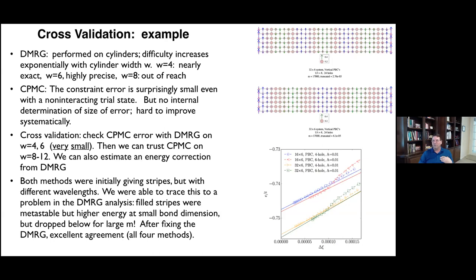So they both have 24 holes, but the top one has them divided into 6 stripes with 4 holes, and the bottom one has them divided into 4 stripes with 6 holes. Okay, and these are both metastable within DMRG. And the normal way we resolve this sort of thing is we look at the energy. So in comparing with the Monte Carlo, first of all, we found that the Monte Carlo seemed to be doing very well. But the Monte Carlo was coming out with a different answer than we were getting with DMRG as to which of these two were lower in energy.